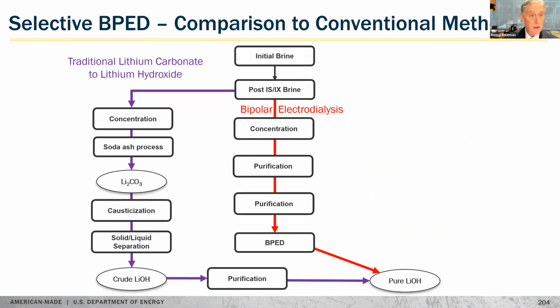So just to put this in context, this slide shows on the far left-hand side the traditional lithium carbonate to lithium hydroxide process. So you would come with an initial brine, and after some cleanup, such as ion exchange, it would go through a concentration step to make lithium carbonate, and then the lithium carbonate would be converted to lithium hydroxide. The conventional bipolar electrodialysis process takes that same ion exchange and somewhat cleaned up brine and puts it through rigorous concentration and extensive purification to remove those divalent ions that cause the scaling and fouling that shut down the membranes before going to bipolar electrodialysis to make the lithium hydroxide directly.